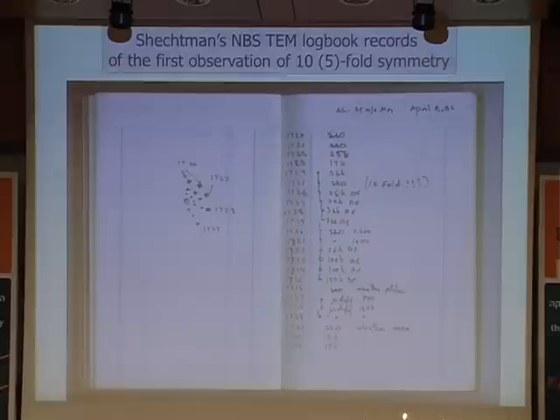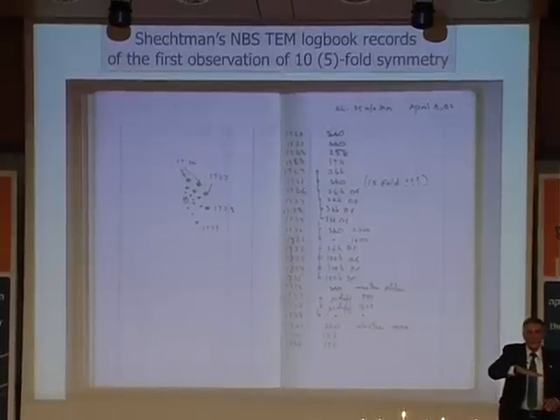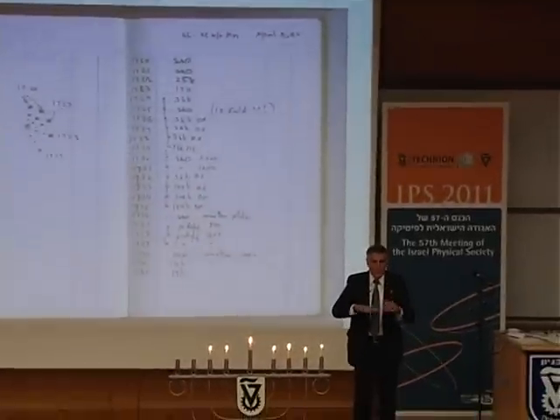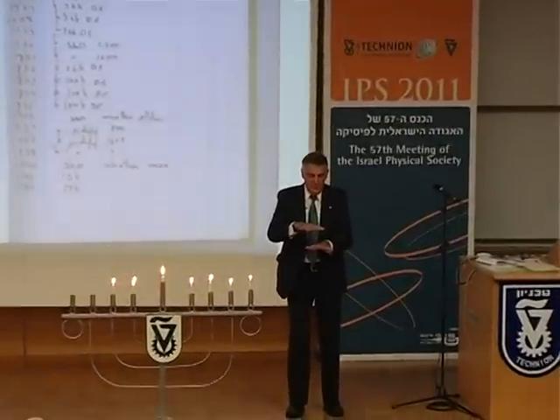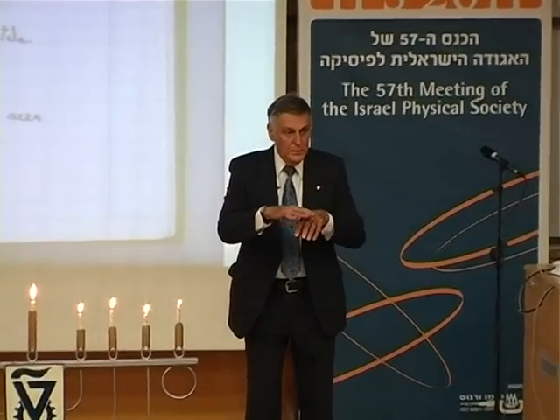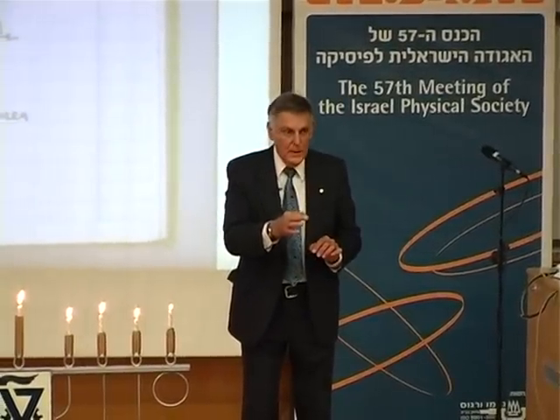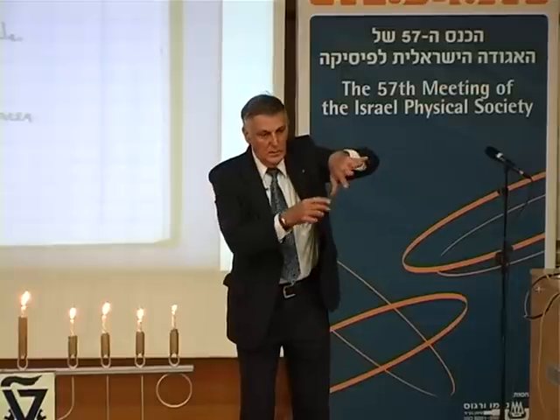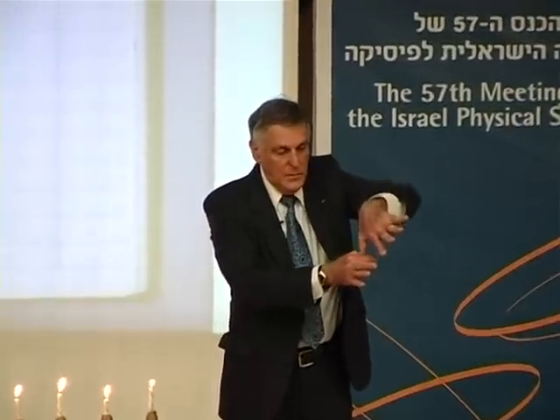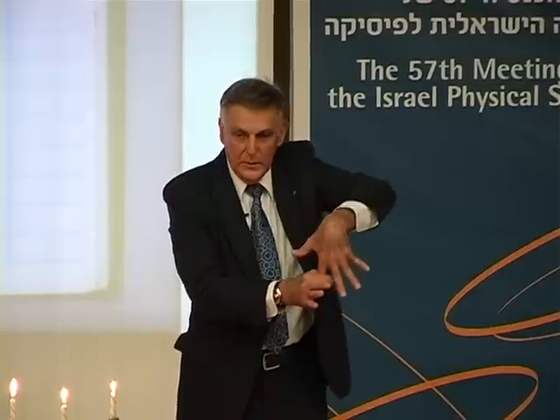Let me explain a little bit about electron microscopy. In an electron microscope, you have a specimen which is transparent, and the beam penetrates through. This is why it's called transmission electron microscope. And under the specimen, part of the beam goes through and part diffracts. And there is an aperture there called the objective aperture. Let's say that all these are diffracted beams, and this one here is a transmitted beam. And there are many of them. So if I let the transmitted beam go through and form an image with a transmitted beam, we call it bright field image. Transmitted beam, bright field image. But then you can tilt the beam so that one diffracted beam will go through. And then if you form an image, it's called dark field image. Now, if you form a dark field image, then the bright part of the image is the part that contributed to that diffracted beam.